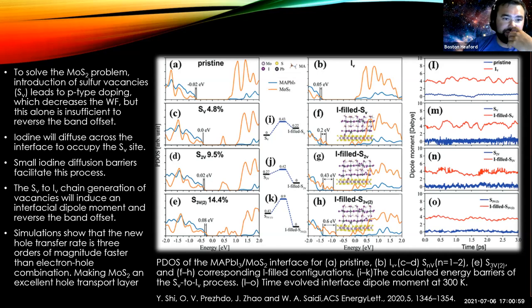These are just a bunch of graphs showing different concentrations of doping and their effects on the systems, and they're all at 300 Kelvin. Mostly, what are the blue and orange lines in the panels? In the first row, or first column, I mean? Those are the partial density of states: the blue is the perovskite, and the orange is the interface, the molybdenum sulfide. It shows that as you increase the doping, the gaps get smaller and smaller.